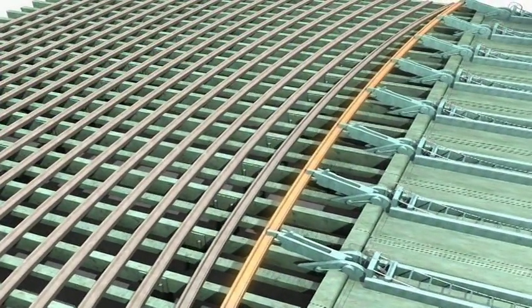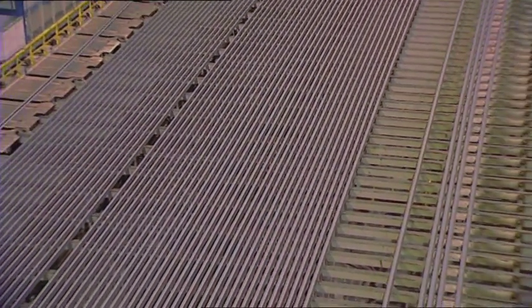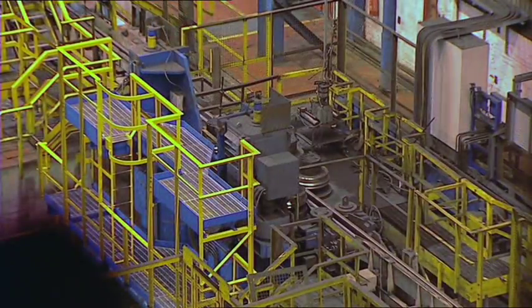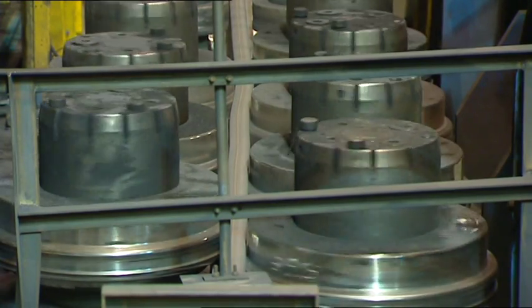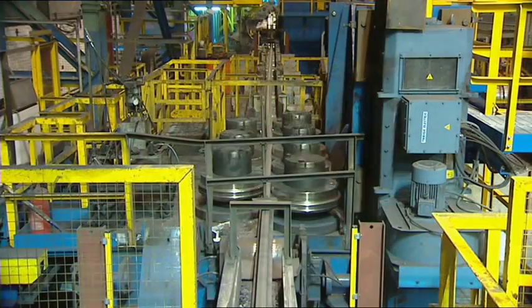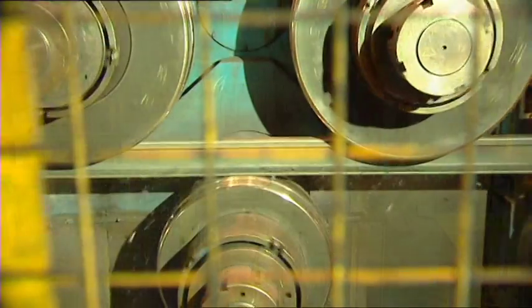The rail is then moved to the cooling banks, where it is pre-cambered using computer-controlled pre-cambering systems. This compensates for the natural curvature that occurs as the rail cools and ensures the optimum rail characteristics prior to rail straightening. Straightening is undertaken in a highly instrumented dual-plane straightener. Loads and deflections are recorded on all rails, while single-piece high-chrome rollers, coupled directly onto the spindle via a tapered hydraulic locking sleeve, ensure that the process produces a straight, flat, low-stressed product.